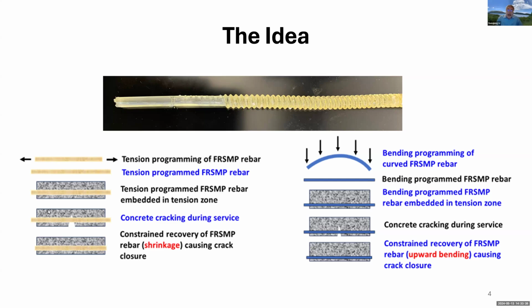Now, by triggering the shape recovery process, because remember, this is the length of the rebar after the pre-stressing, when the shape memory effect is triggered, this longer rebar tries to go back to the original length, which means that the rebar tries to shrink. When it shrinks, it will bring the crack in touch, or at least narrow the crack. So in such a way, the rebar is not only a load carrying device, but also a functional device to help close cracks. If the cement concrete is self-healable, then the crack can be self-healed. Okay, so that's the major idea.